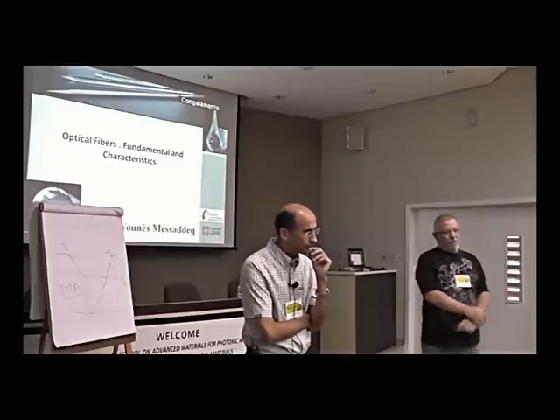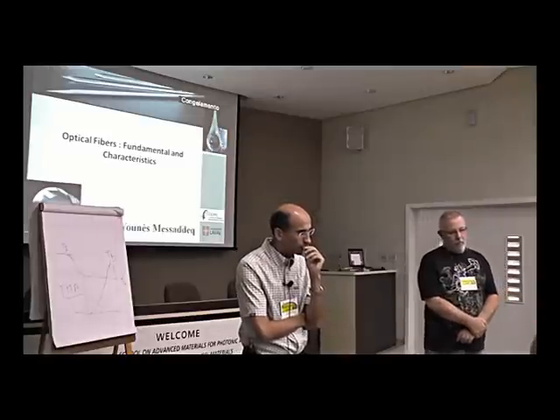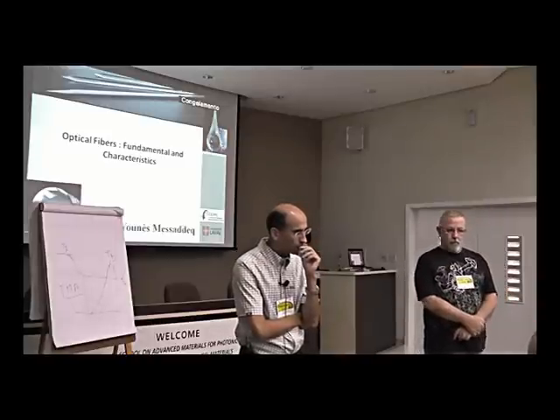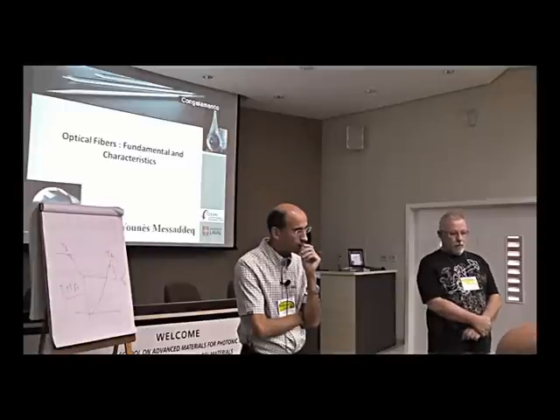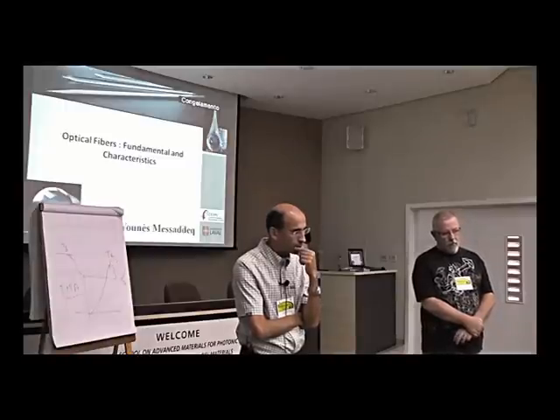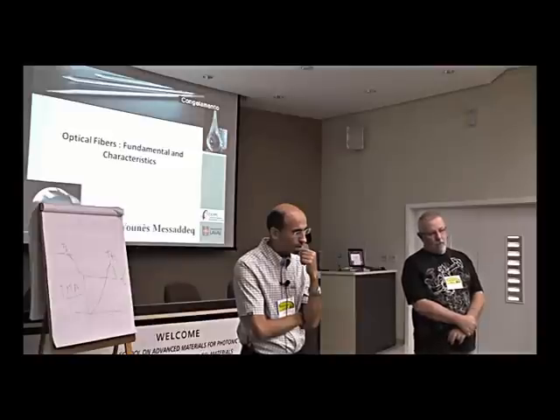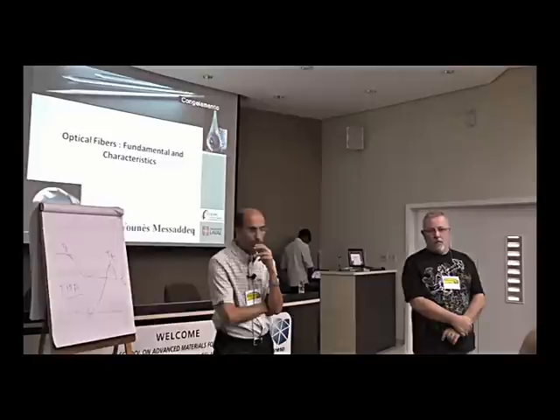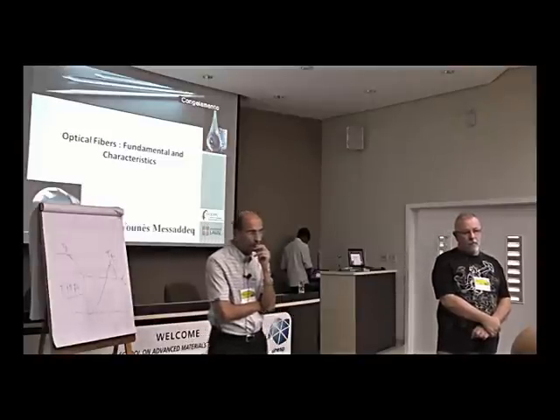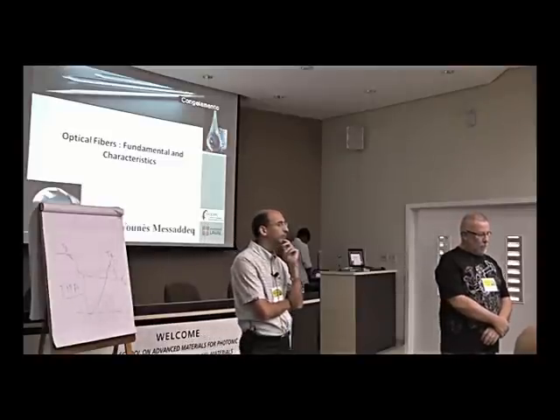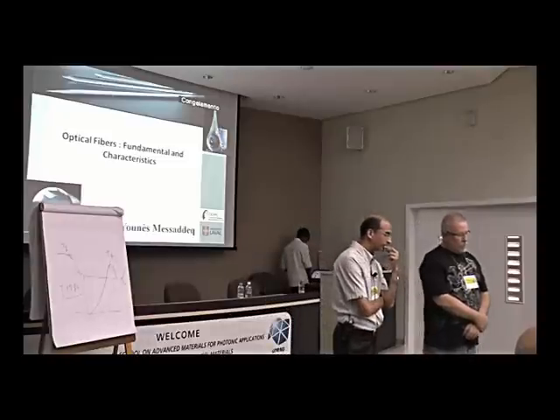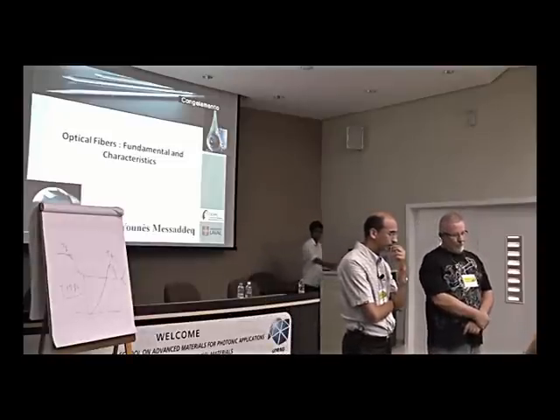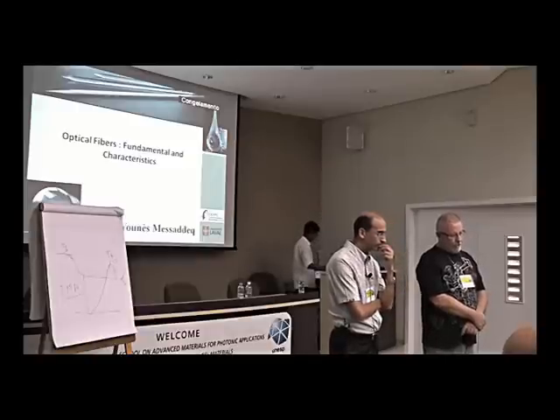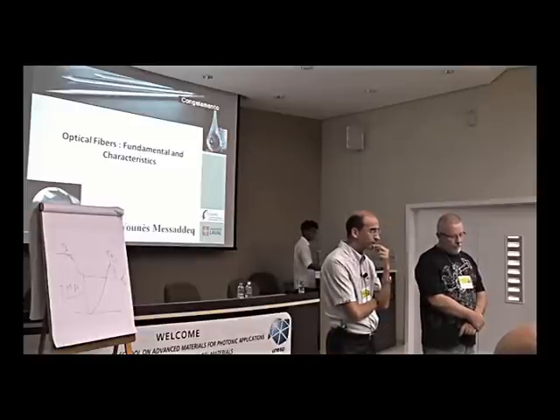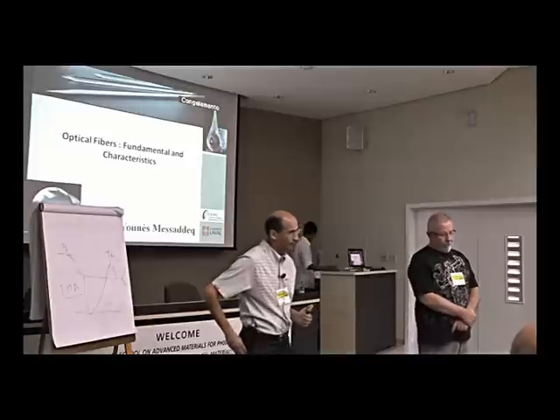I think we use that, but in fact there was some mechanical problem of fibers. Actually, it's the case. You decrease by reducing the fictive temperature. Reduce the Rayleigh scattering. We show that, but there is some mechanical problem. That's right, that's true. That was done regularly in the early days to just reduce Rayleigh scatter because of fictive temperature. But yes, you're right, there were issues. And I think sometimes you do use it when you want a specialty fiber, and mechanical strength is not an issue.